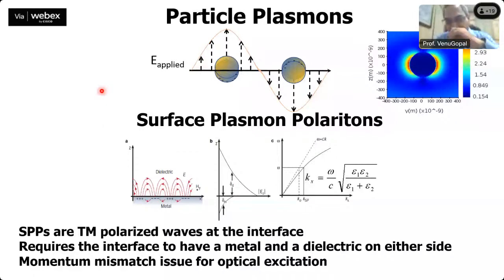So during the positive half cycle of the applied electric field, the electrons are pushed down, and during the negative half cycle, you can see that these electrons are pushed up towards the top of the metal nanoparticle. We obviously know that the electrons are not moving away, they are still confined to the metal nanoparticle, but just oscillate about the mean position. Right? So the consequence of exciting these particle plasmons, the collective oscillation of these electrons on the surface of the metal nanoparticle, is that we see a strong localization of the field.